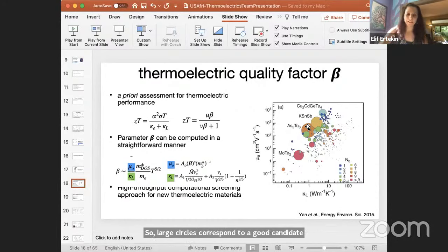So the main idea is that by using beta, it's relatively easy to try to identify thermoelectric material candidates. In the past, it's been used to rediscover many already known thermoelectrics and has also predicted several new ones that have since been verified in the lab.